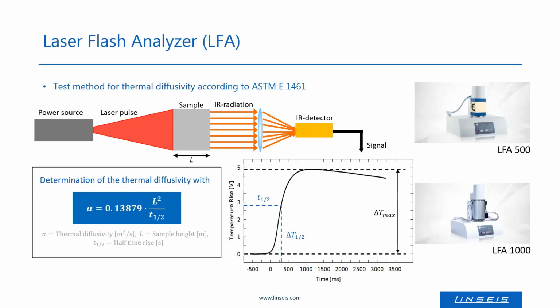So in the next slides, I will shortly show you the working principle of the thermal conductivity measurement instruments. So in the laser flash measurement, one has a power source which shoots a short high energy pulse onto one side of the sample. Here the energy is then absorbed and a part of the energy is radiated onto the other surface of the sample, and this radiation is detected by an infrared detector so that one achieves a signal like that. And this signal is used then for the thermal diffusivity calculation, where also the thickness of the sample is of interest.